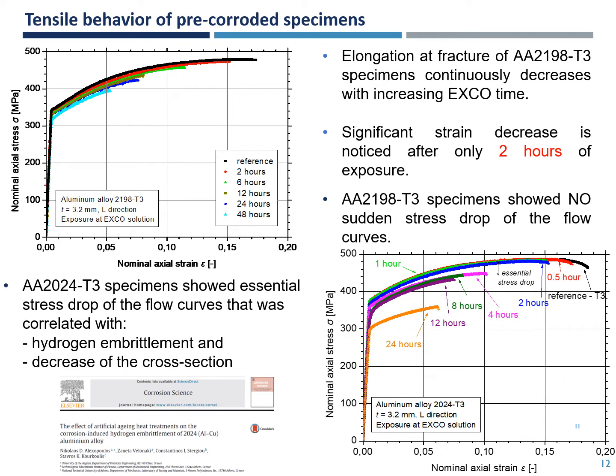This degradation was correlated with hydrogen embrittlement and degradation of the cross-section of the specimens. However, regarding aluminum alloy 2198 in T3 condition, no sudden stress drop of the flow curves is noticed even after the highest exposure time of 48 hours. Elongation fracture of aluminum alloy 2198 specimens continuously decreases with increasing exposure time, and a significant strain decrease is noticed after only 2 hours of exposure, shown with the red curve in the left figure.